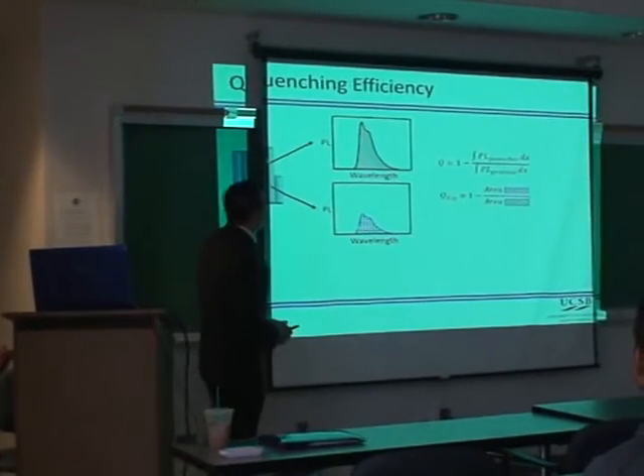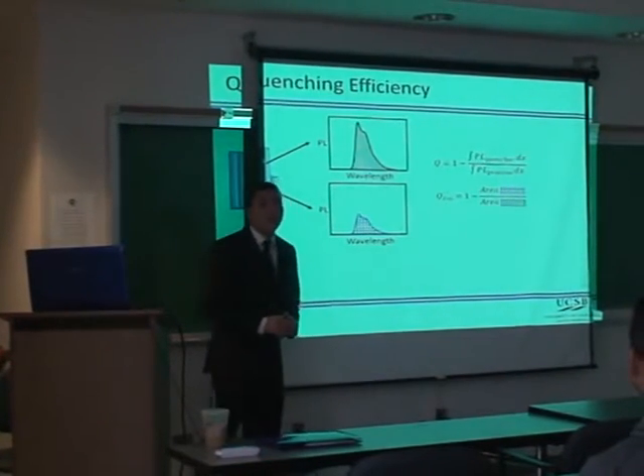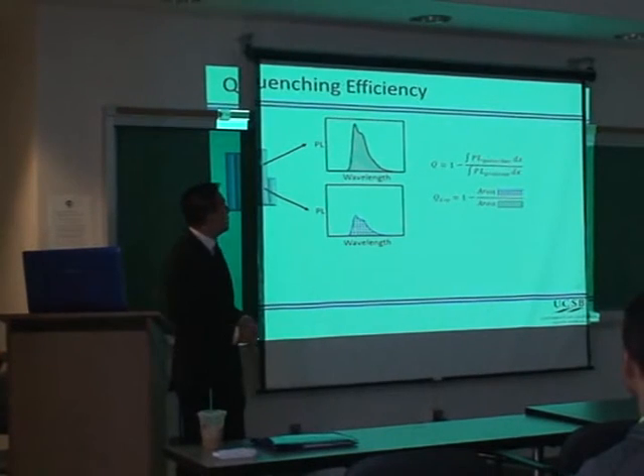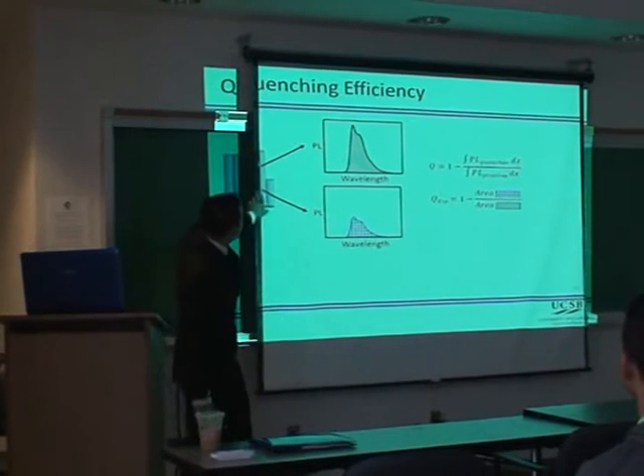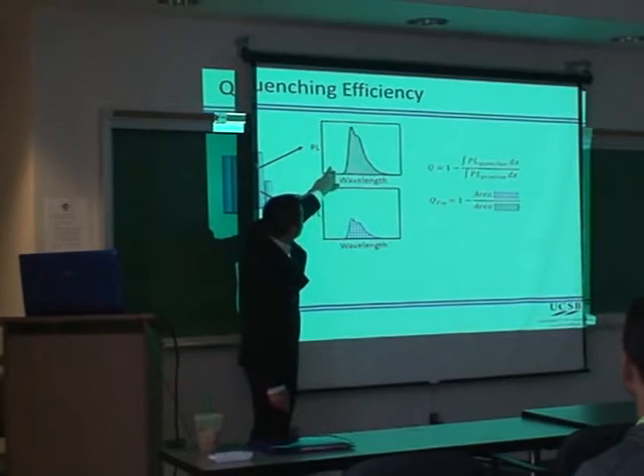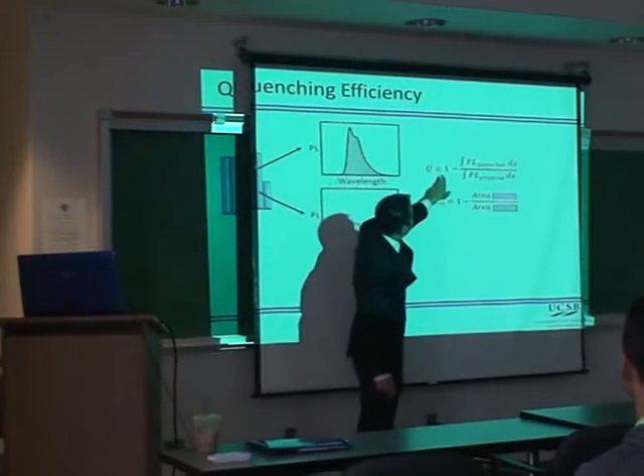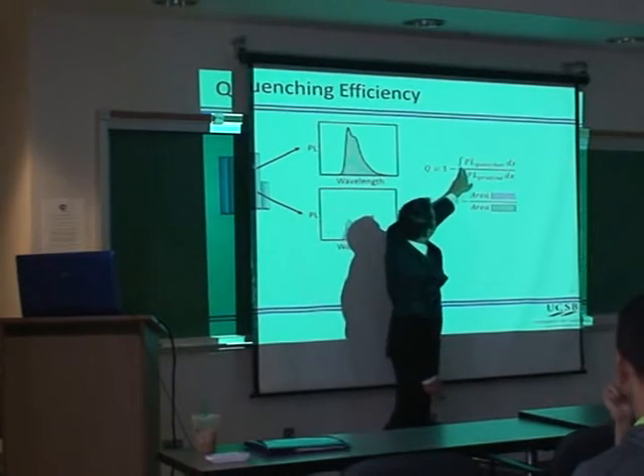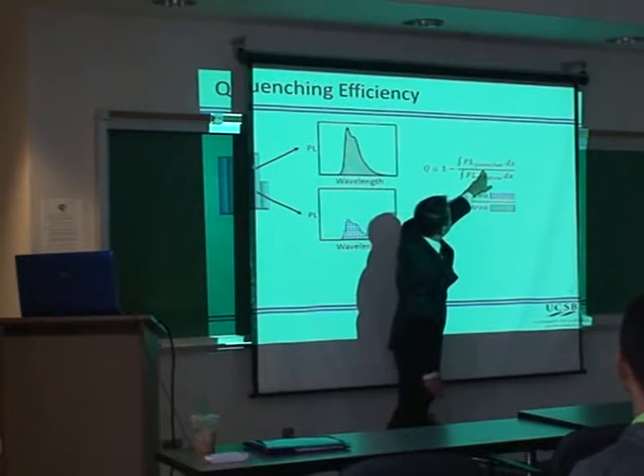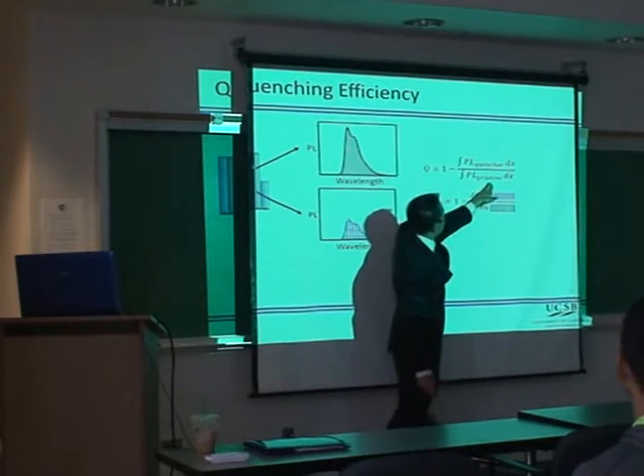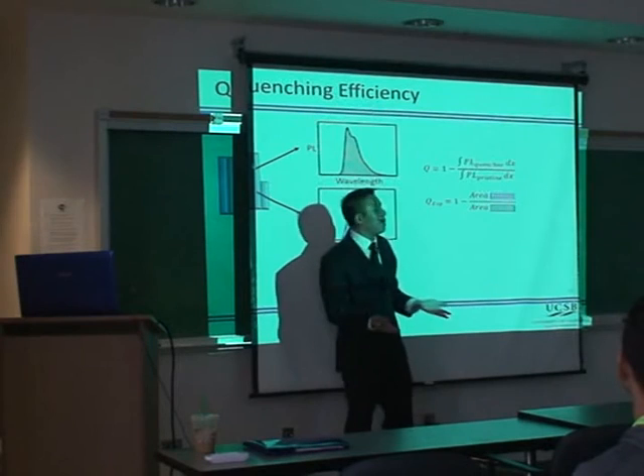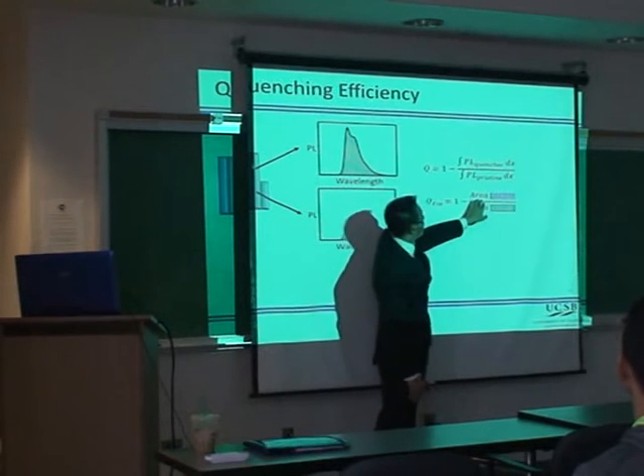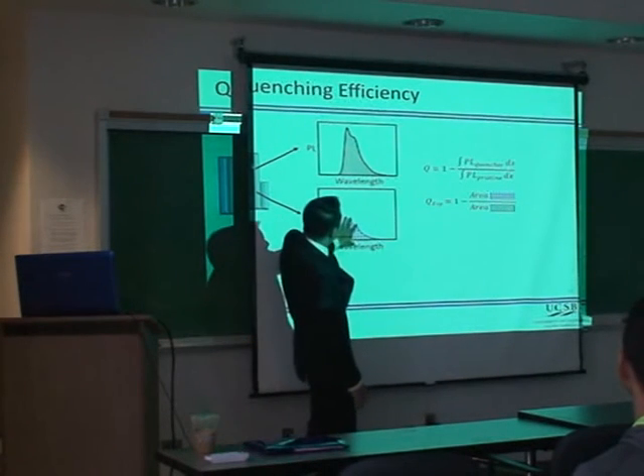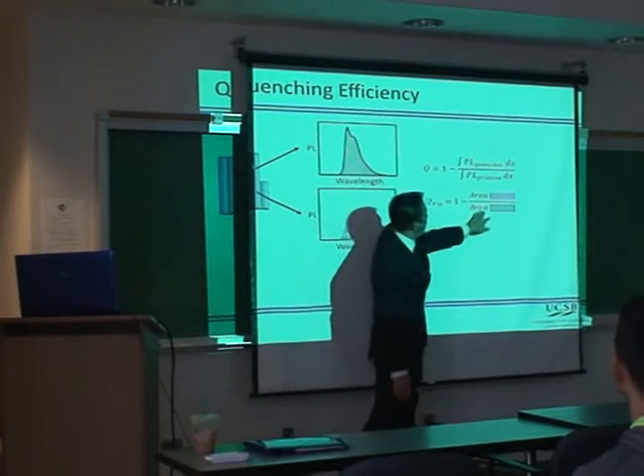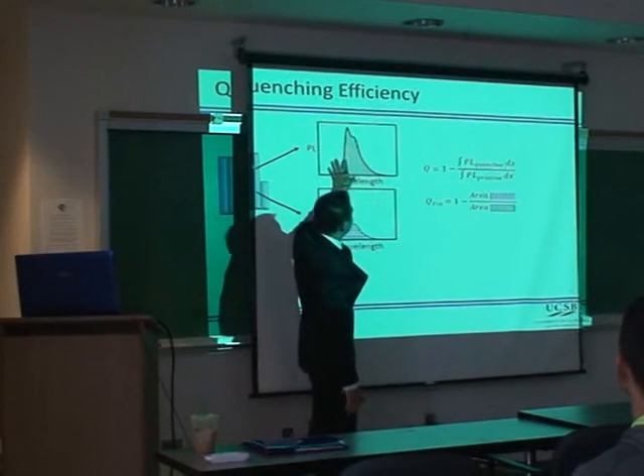So now the next question is, what can we do with this data? Well, one thing you can do is calculate the quenching efficiency. And as I mentioned, you have these two different locations, and you could use this formula to calculate the quenching efficiency. Basically, this is the integral of the PL with the quencher over the integral of the PL with the pristine. A way to simply think about that is that it's basically the area of the blue, the film with the quencher, over the area without the quencher.